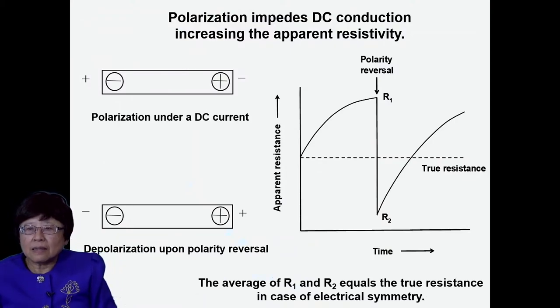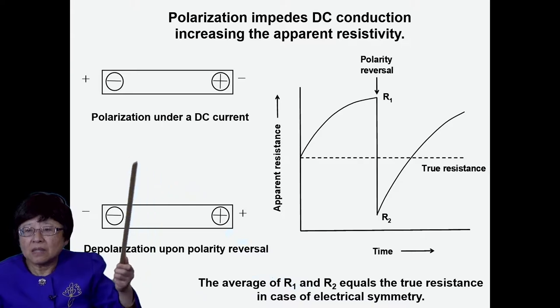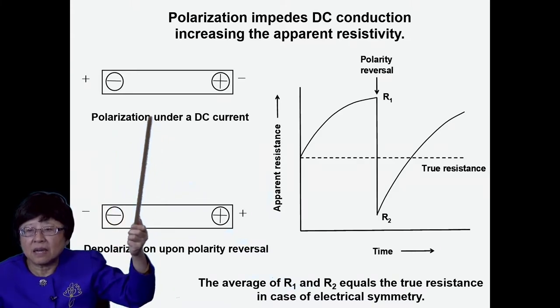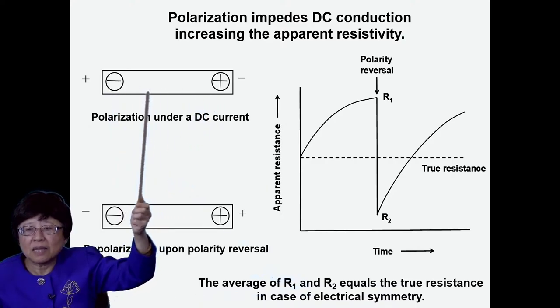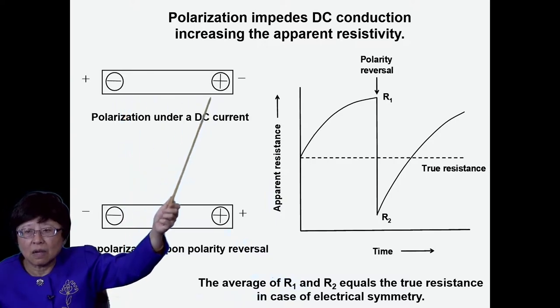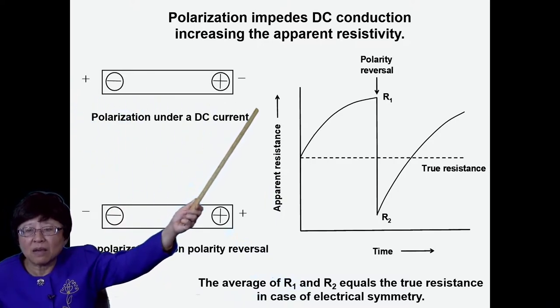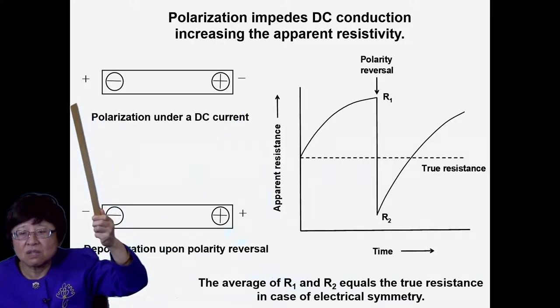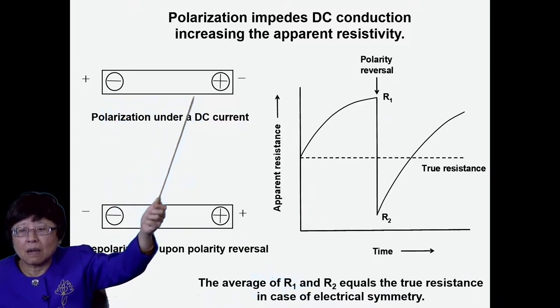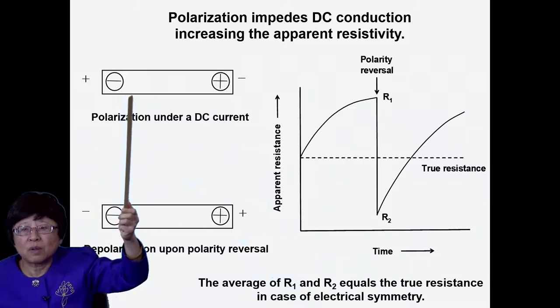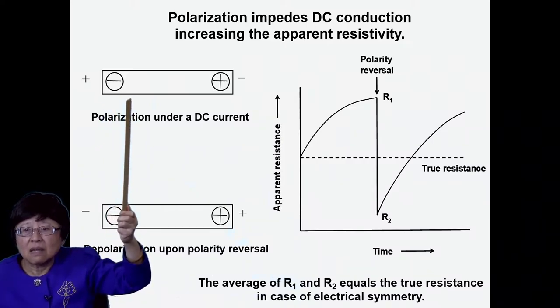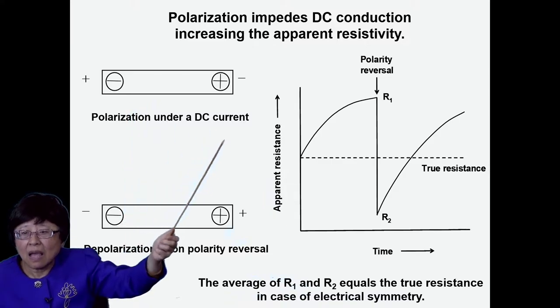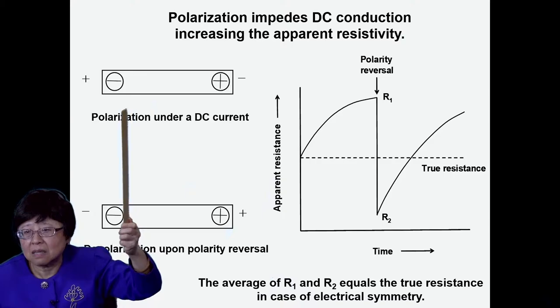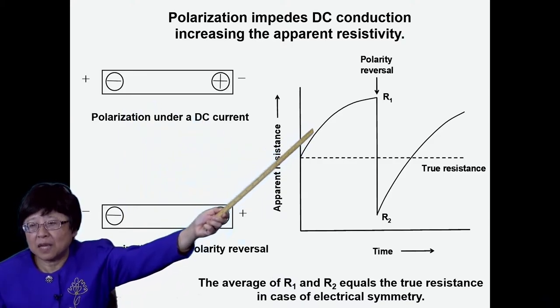The polarization impedes DC conduction, therefore increasing the apparent resistivity. This is with polarization under a DC current. So the circled plus, circled minus represent the negative and positive charge centers resulting from the polarization. This plus and this minus without the circles indicate the applied voltage. So the polarity of the dipole due to the polarization is against conduction, and so it causes the resistance to appear to be high, higher than the true resistance. And so as polarization takes place, that is, as this dipole builds up, the apparent resistance climbs up continuously.